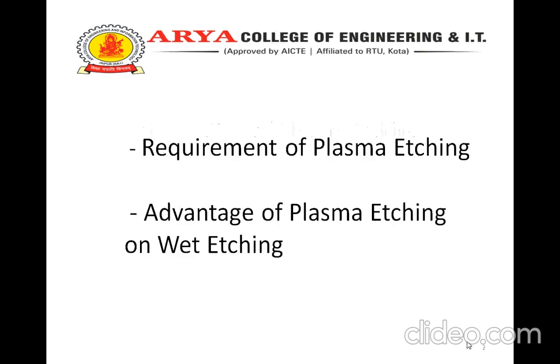Requirements of plasma etching. Three important requirements in etching are selectivity, anisotropy, and uniformity. A very large number of species are created within plasma etching. The reduction in the degree of specificity of the reactions, compared to a pure chemical process, is considerably reduced. So the degree of selectivity in a plasma process is relatively poor, and endpoint detection techniques have to be necessarily employed in plasma etching systems.